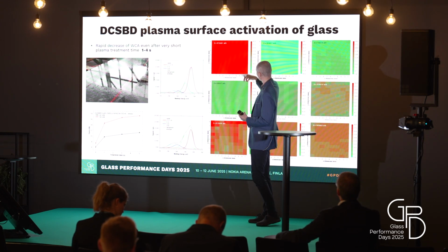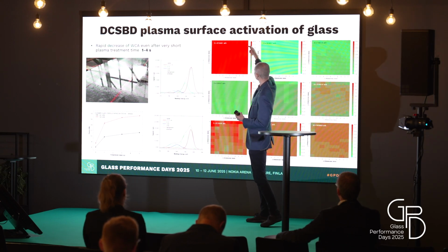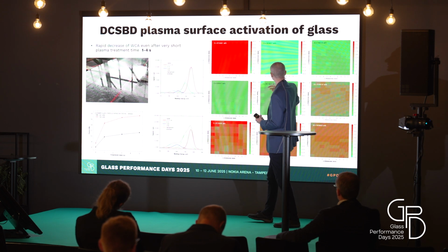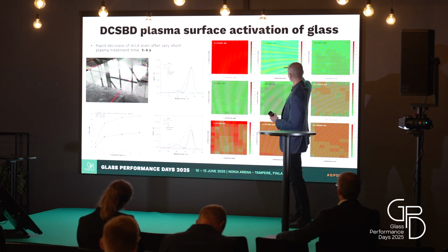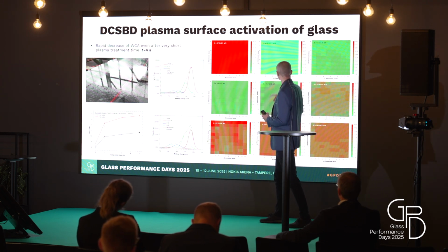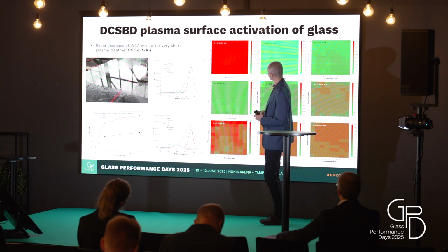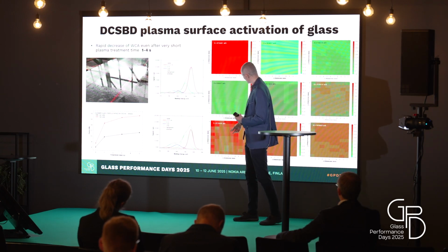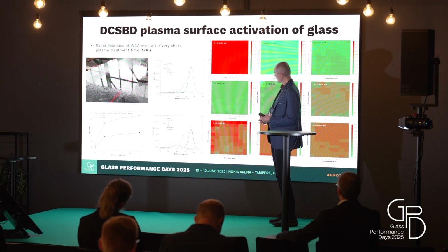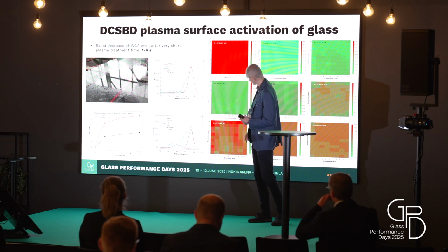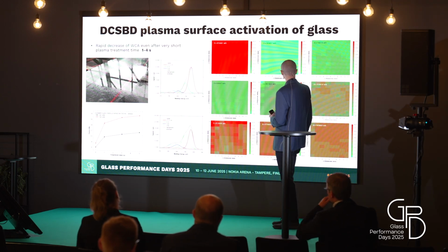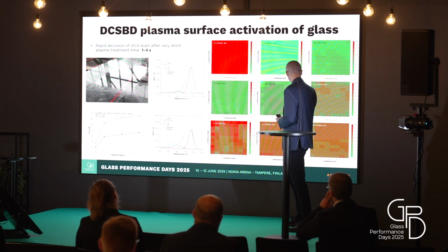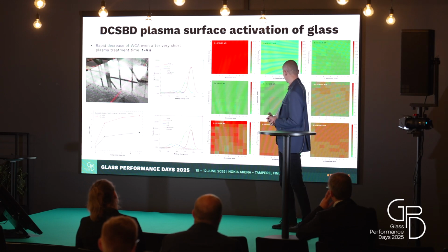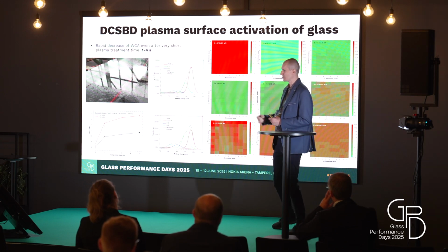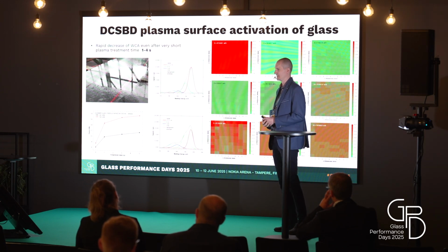This color change represents the decrease, for example, of the carbon to a lower concentration of carbon, and an increase in the oxygen to carbon ratio. This is the carbon signal. And when we compare this image to this one, we also clearly see the improvement of the uniformity, for example, when you compare here. Unfortunately, this display doesn't look so nice, for example, over there.